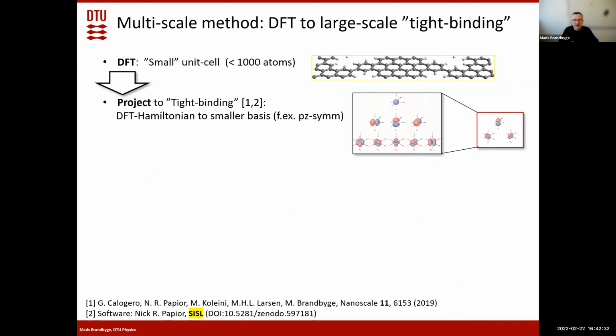So in order to simulate these systems, we start with density functional theory again and do a calculation on a smaller unit cell. It could be bigger than this one, but some smaller structure, let's say maximum 1,000 atoms or something. And then we have ways to take out just the orbitals we need. So we can project it into what you could call a tight binding, but it's a tight binding which actually fits completely with the DFT calculation. So we can make a smaller Hamiltonian out of this building block.